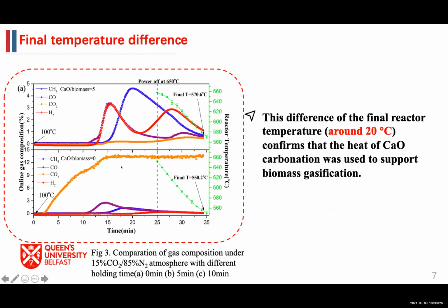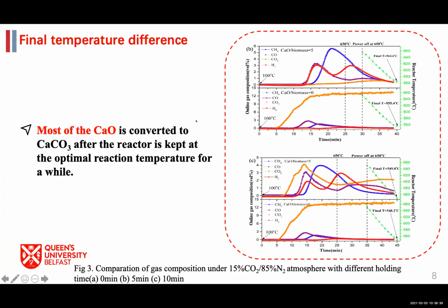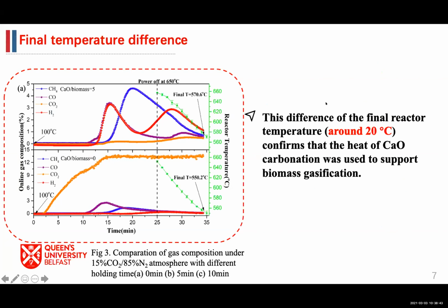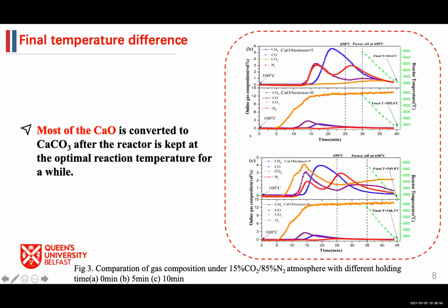So from the results, we can see that compared with traditional biomass gasification, in our process most of the CO2 was converted into syngas products. And what's more interesting is that after shutting down the reactor power, the final reactor temperature difference showed around 20 degrees, which confirms that the heat released from calcium oxide carbonation was used to support biomass gasification. I also did some comparison work under different holding times. From the results, we can see that after holding for 10 minutes at the optimized temperature, there's almost no final reactor temperature difference because most of the calcium oxide is converted to calcium carbonate, which is reasonable.